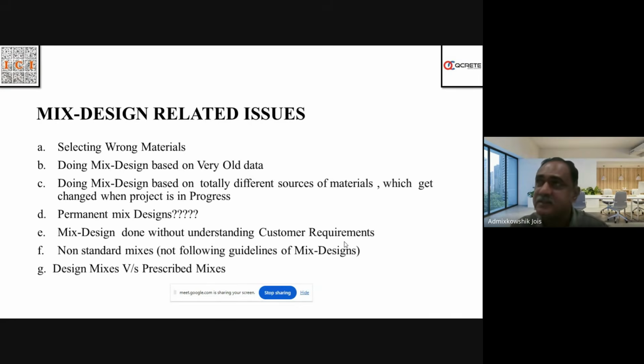You should not have permanent mix designs. For example, a project is running for 4 years. It is not necessary that the M40 mix we did at the beginning of the project with some trial mixes will hold. You cannot have the same thing for 4 years because materials will change, all the ingredients will change. They may most likely change. So your mix design has to be based on your observation of the cube results, and you also observe the slump, both fresh and hardened properties, and this is referred to as retrospective control.